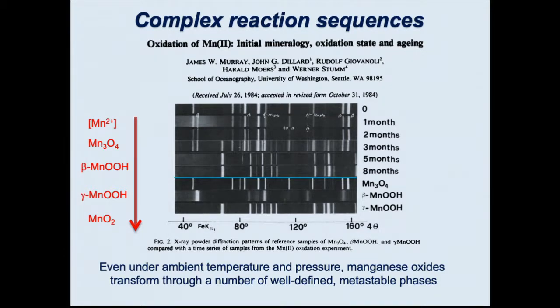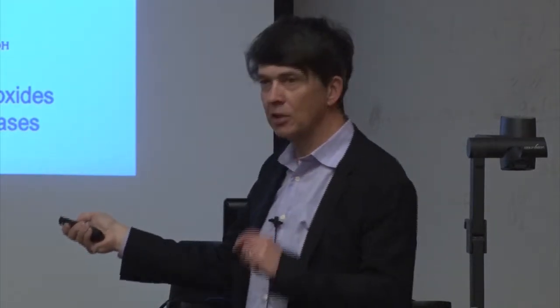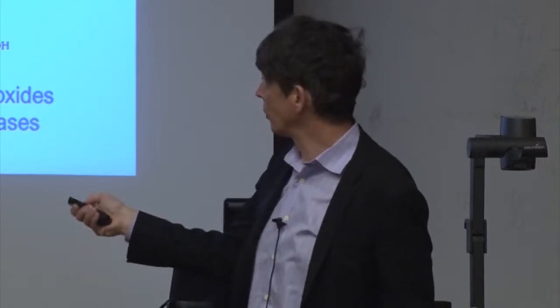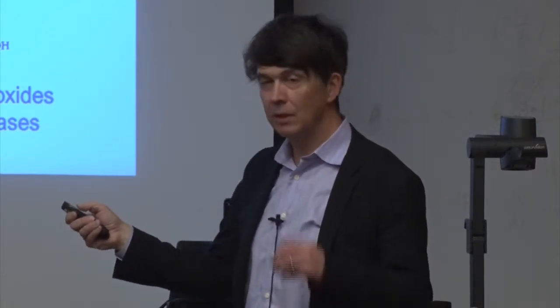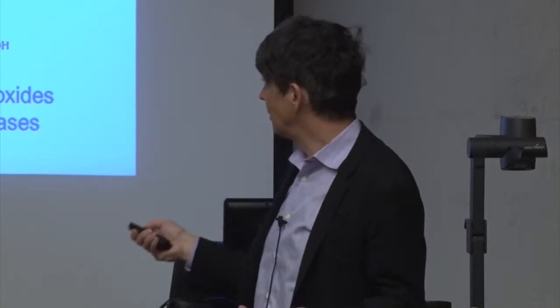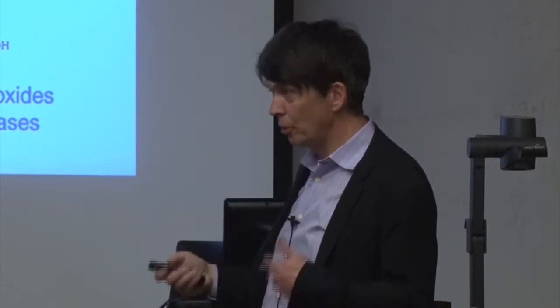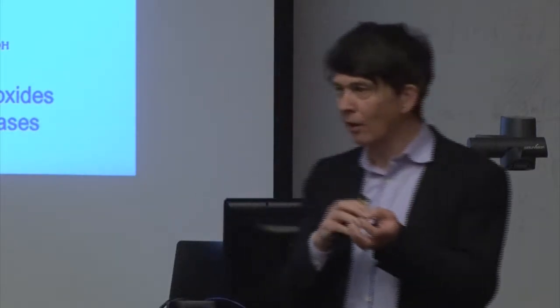it finally forms MnO2. By the way, if you take a Pourbaix diagram, which is a phase diagram for solutions, right, it should form MnO2. So by here it has actually formed the equilibrium phase, but look, it went through 1, 2, 3 intermediates. And these are well crystallized, right? Look at this, it's a pretty sharp diffraction line. This is not some gooey gunk that formed on the way to the MnO2 formation. This is well-formed crystalline phases.